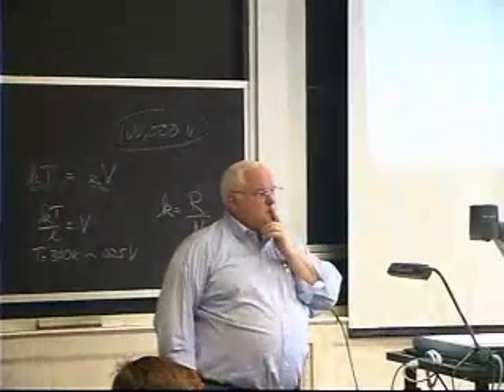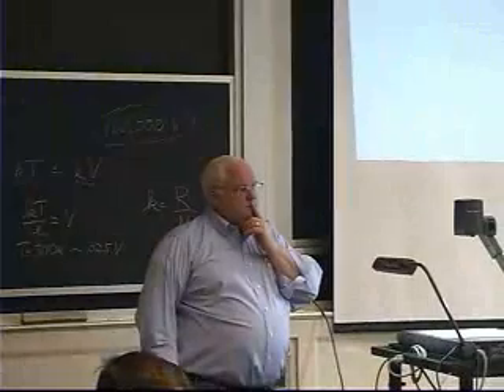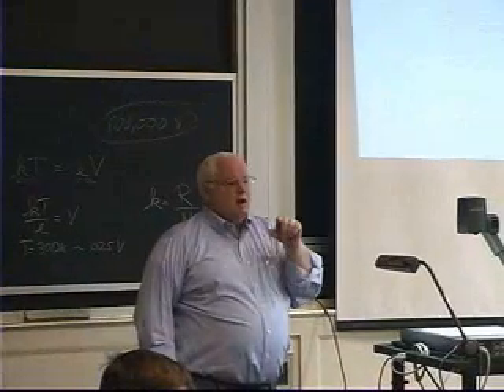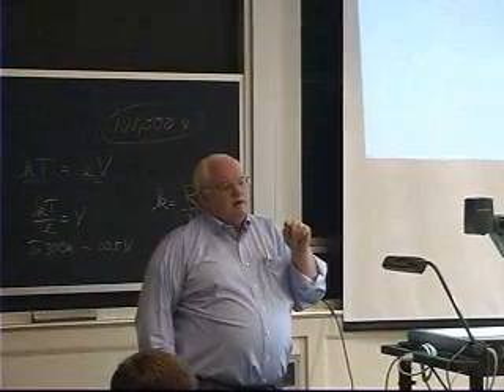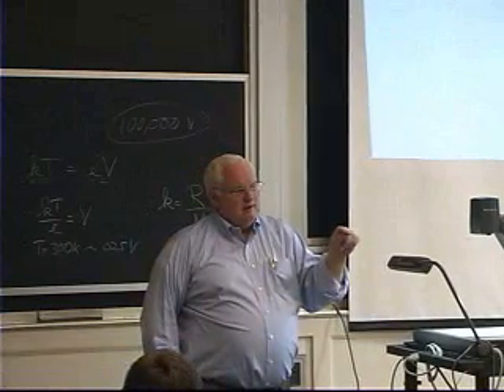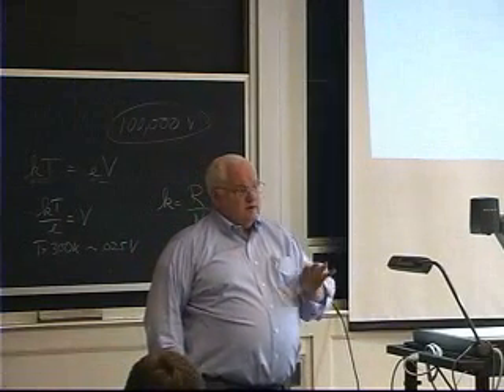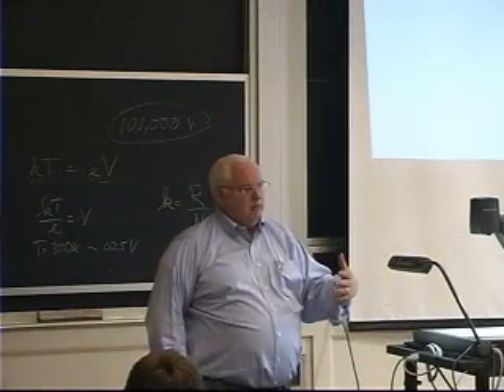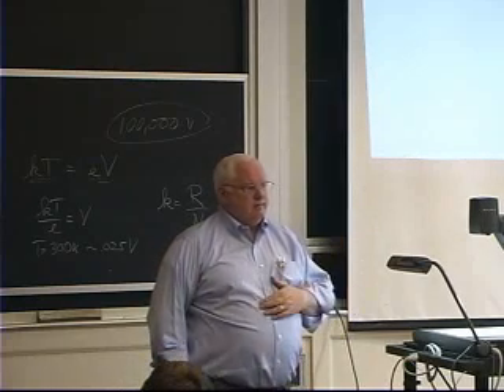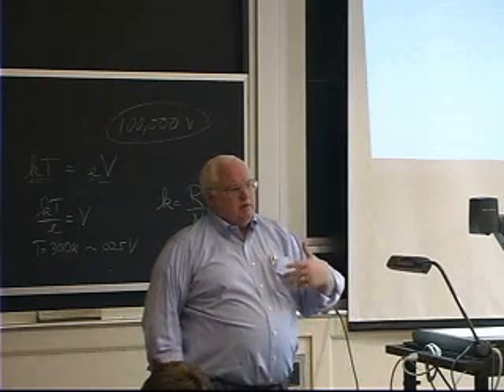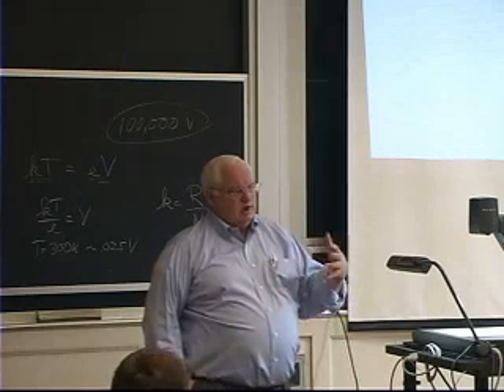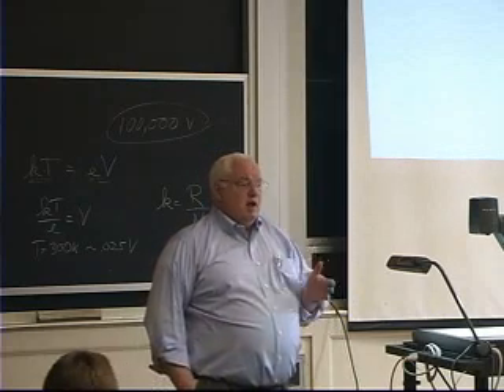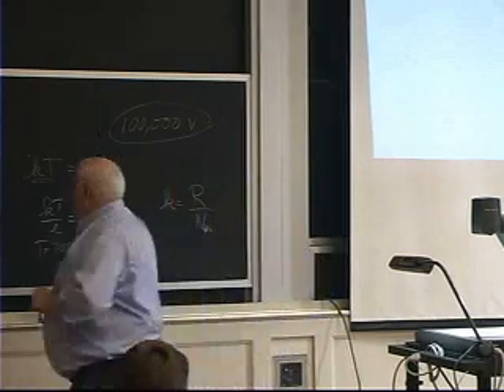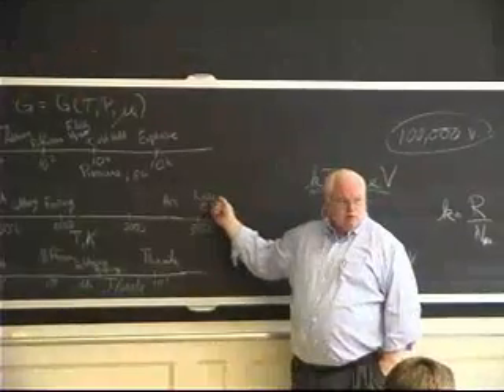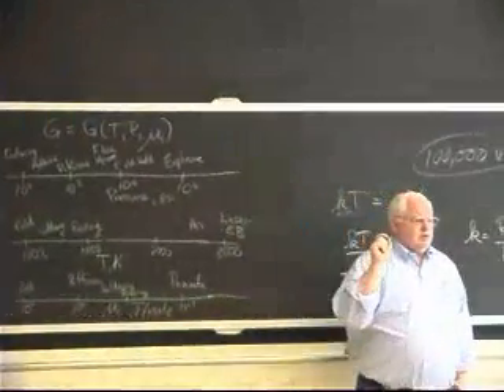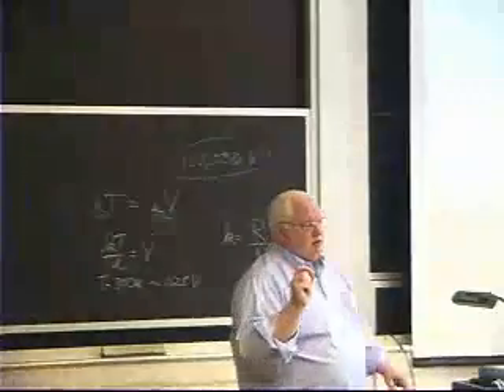But doesn't it shrink the heat affected zone if it doesn't transfer out? No, because that electron bounces around and hits more and more atoms, and eventually gives up its energy, but not all to one atom. And it actually has a depth of penetration. When you get to electron beam welding later in this course, we'll talk about what the size of the heat affected zone is and how it gets controlled. And most of the stuff you read in welding will say when you go to very high heat intensity processes like laser and electron beam, you can shrink your heat affected zone down to 0.